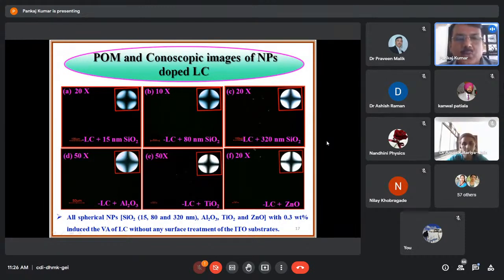Not only the silica nanoparticles, you can see here figures D, E and F: titanium oxide, aluminum oxide as well as ZnO nanoparticles. All the nanoparticles, when dispersed with the liquid crystals to prepare the display cell without any coating, without any baking, without any specific treatment, you can achieve the vertical alignment in the display cell.